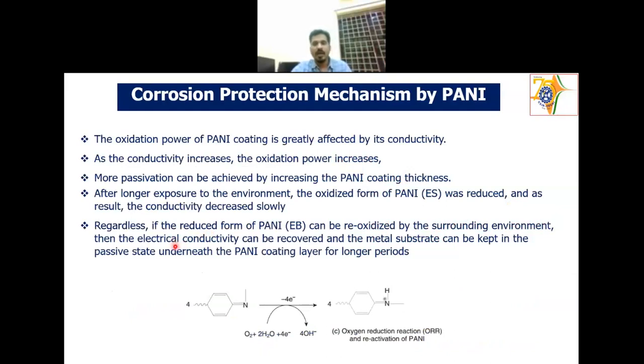And then another one is the cathodic protection. How it is offering is, the oxidation power of the Pani coating is greatly affected by its conductivity. If it's more conductive, its oxidation power is higher. How to make it more conducting? You can increase the dopant amount. More passivation can be achieved by increasing the Pani coating thickness, which means more amount of Pani is there. After longer exposure to the environment, all the oxidized form of Pani will be reduced and finally it becomes EB and the conductivity decreases slowly. Regardless of this, there is a possibility that the reduced form EB can be re-oxidized by the surrounding environment. Then the electrical conductivity can be recovered again.